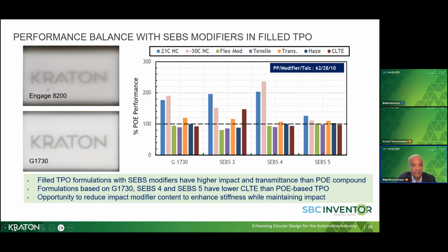The other thing that we notice is with the SEBS formulations, we see much higher notched Izod both at room temperature and low temperature. So what that tells us is we have some room to optimize in terms of modifier content. In this particular case, we increased the modifier content to about 28% from 25% in the unfilled. And we also have opportunity to further modify the talc level, or what we would call optimizing the compound with a certain selection of building blocks. So we would be happy to work with you to recommend formulations and do this optimization to satisfy your requirements.